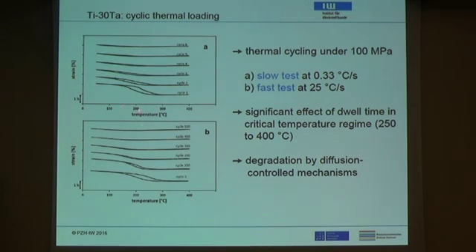Looks pretty much the same, but in the slow test, it takes about 3 or 4 cycles before the material is gone, and now it takes around 300 cycles before you lose the effect. So this tells you it's not the number of cycles that's the problem, it's actually the time. So it's a diffusion control problem. So basically the material degrades because it's kept in this temperature range here for a certain time.